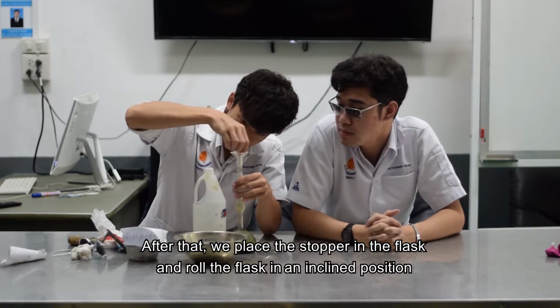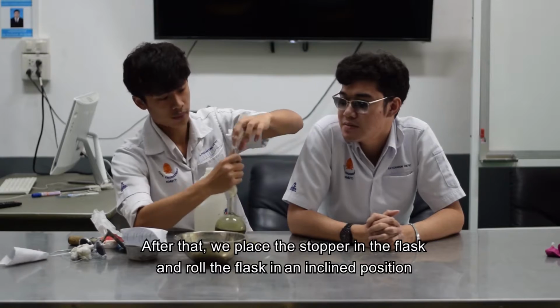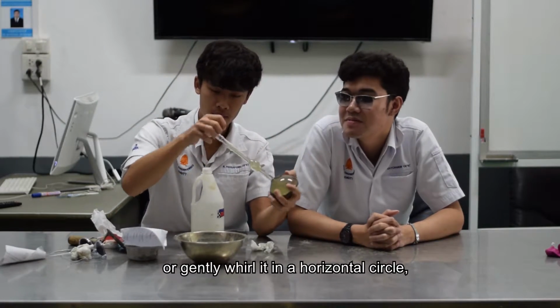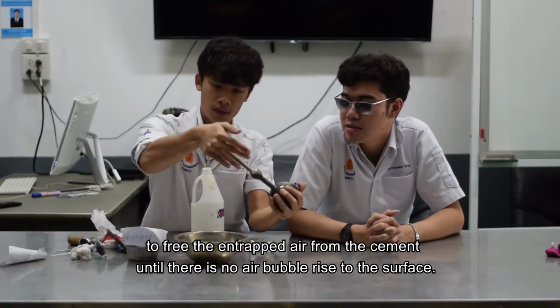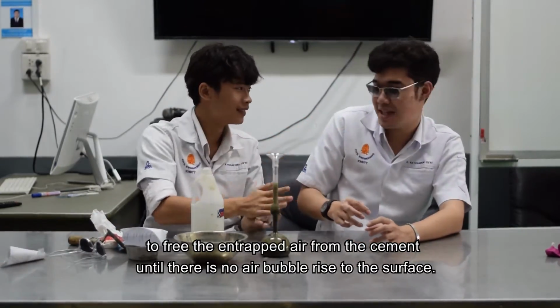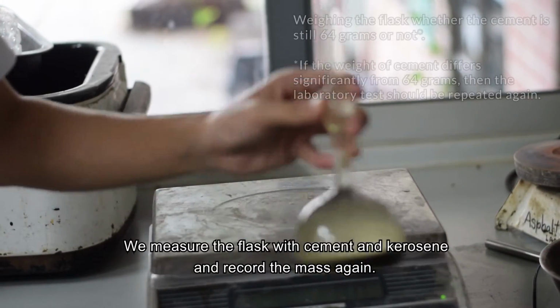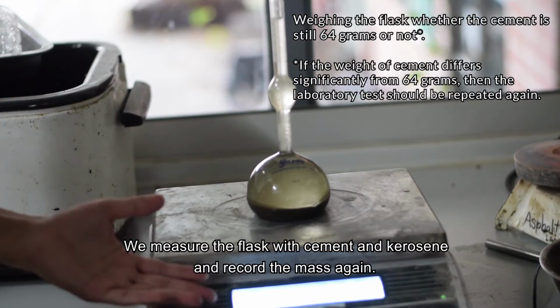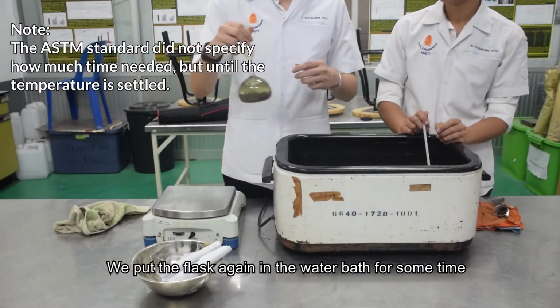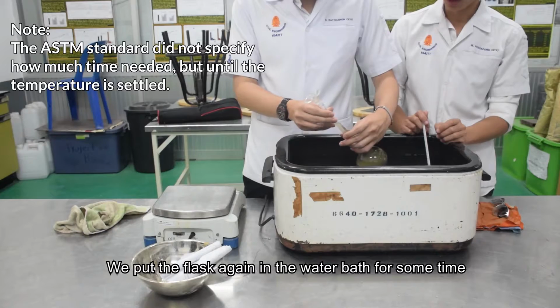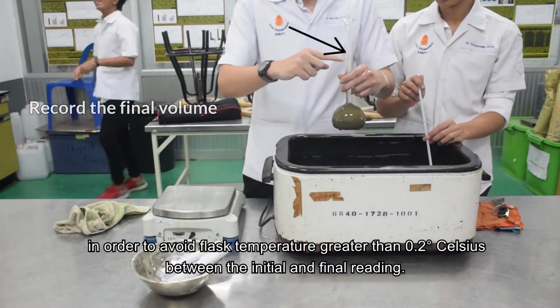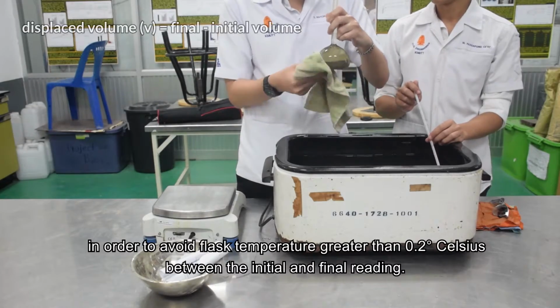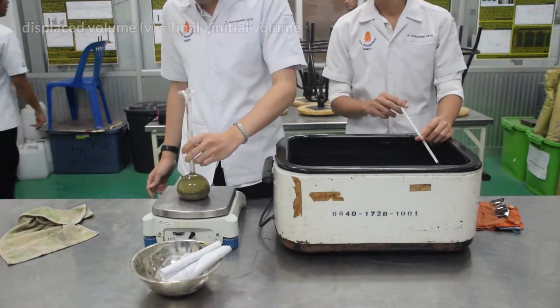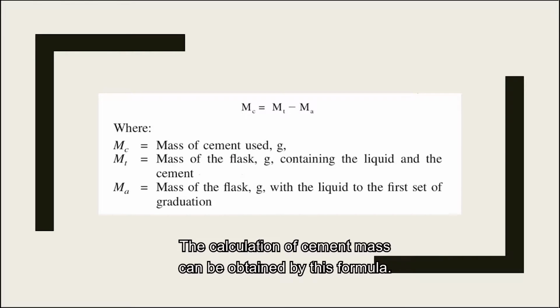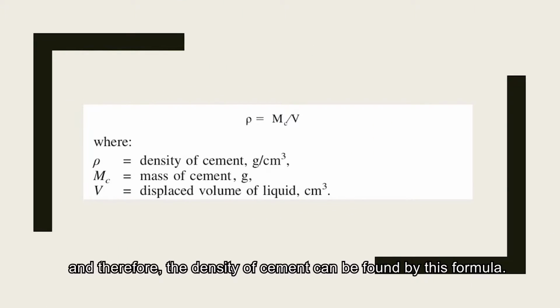After that, we place the stopper in the flask and roll the flask in an inclined position, or gently roll it in a horizontal circle to free the entrapped air from the cement until no air bubbles rise to the surface. We weigh the flask with the cement and kerosene and record the mass again. We put the flask again in the water bath for some time to keep the flask temperature difference no greater than 0.2 degrees Celsius between the initial and the final reading. The calculation of cement mass can be obtained by this formula. And therefore, the density of cement can be found by this formula.